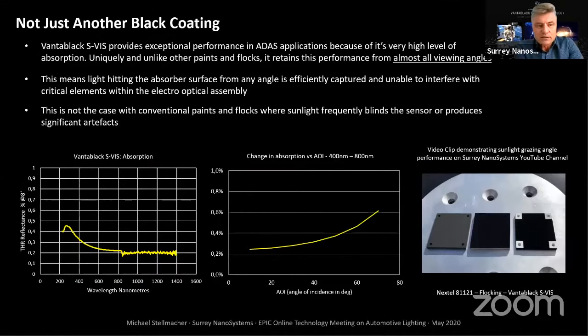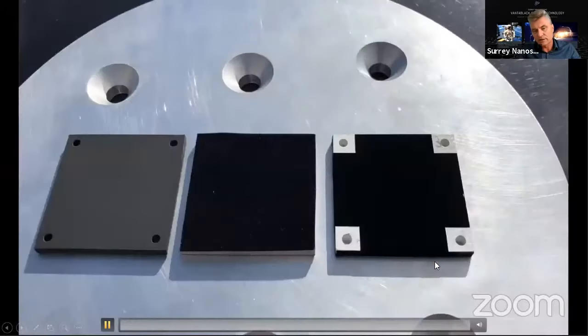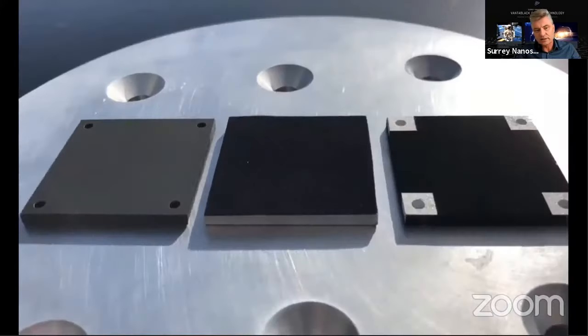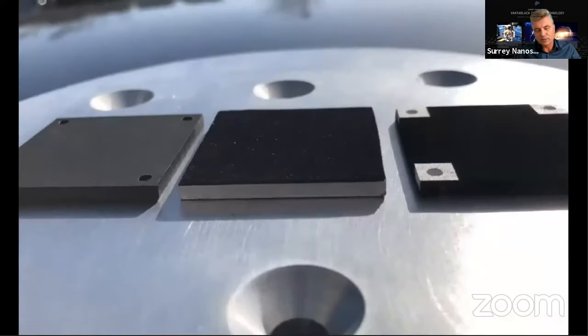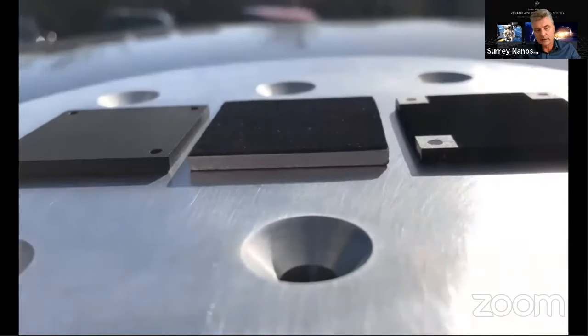The real performance of Vantablack is visible when considering the grazing angles. So you can see in the middle diagram that there's almost no change when the angle is changing. So we're still at 0.6% at 70 degrees incidence angle. And you can see the comparison to the standard coating and to flocking in this very short clip. So when changing the viewing angle, the other coatings become gray, they're sparkling, and Vantablack just stays black.